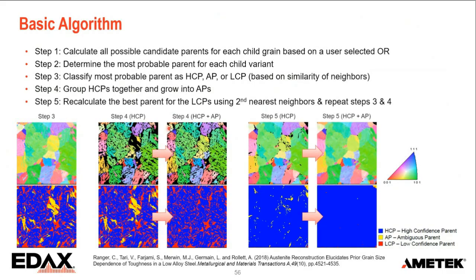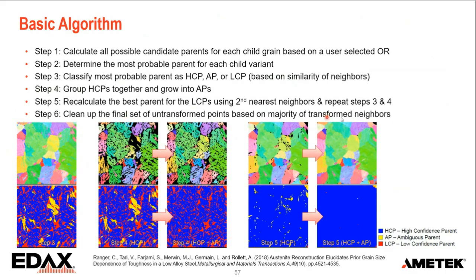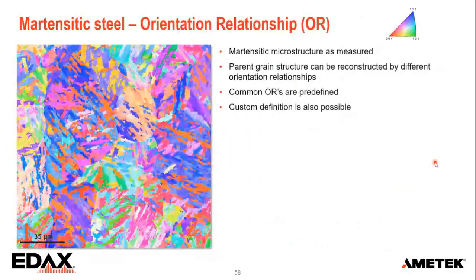And once we have those larger initial austenite grains reconstructed, we can also recalculate these low confidence parents, because again, we have reduced the number of possibilities a lot. We see if there are neighbors that they now match with, and just keep repeating that until we have identified the probable parent for all possible grains. And then in the end, you can do a little bit of cleanup, but that's a choice you can make. So that allows you to go from a martensitic steel like this to that.